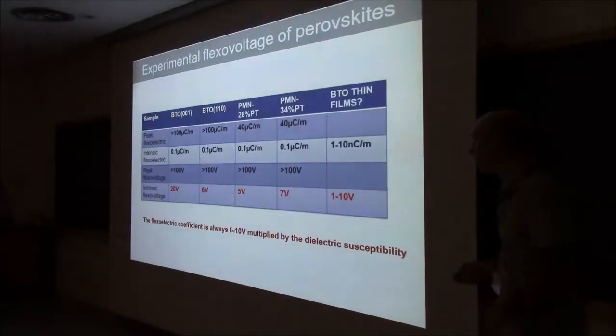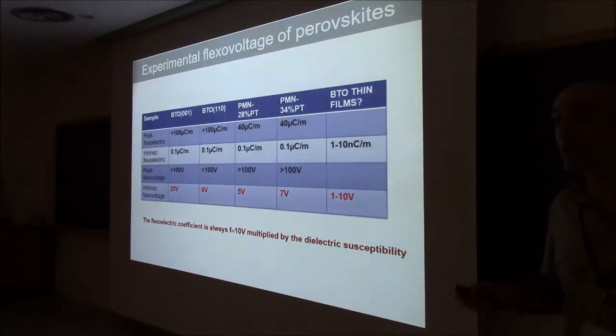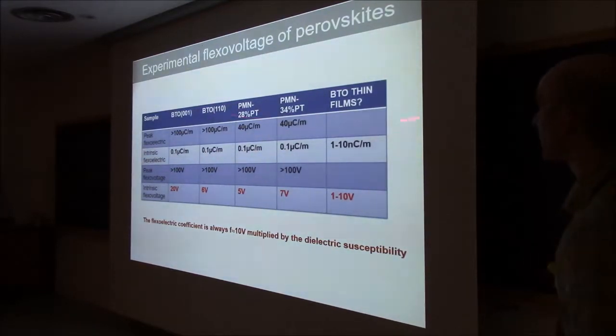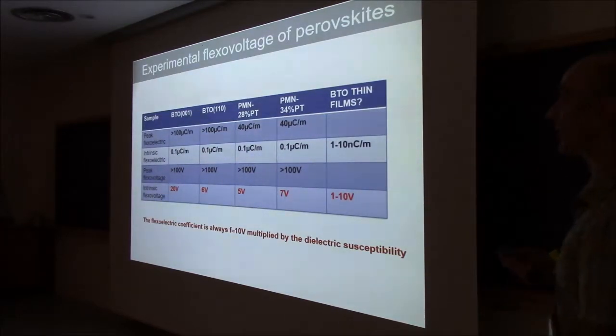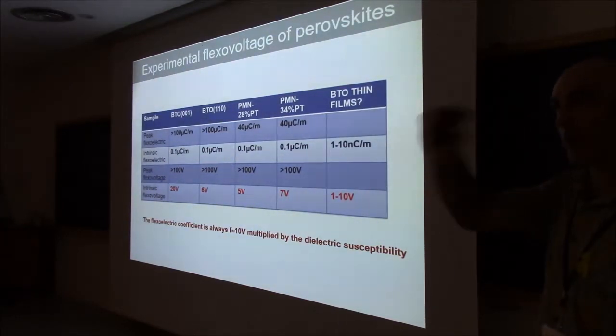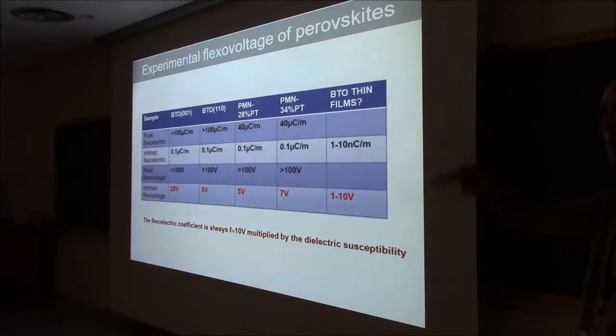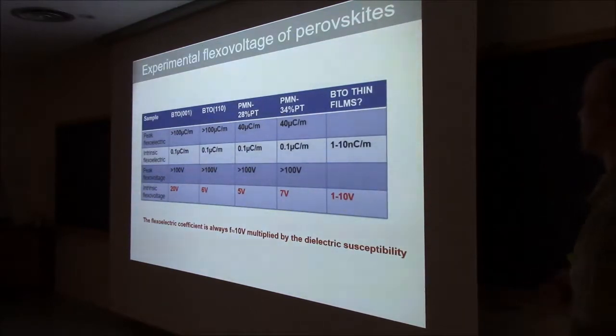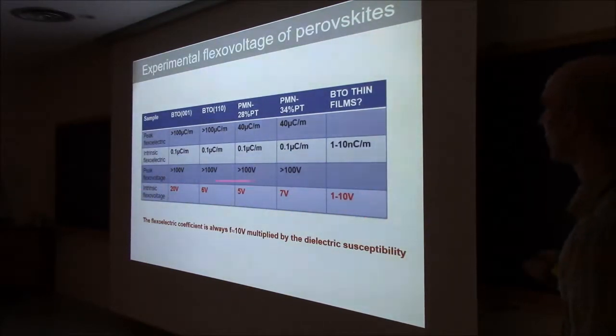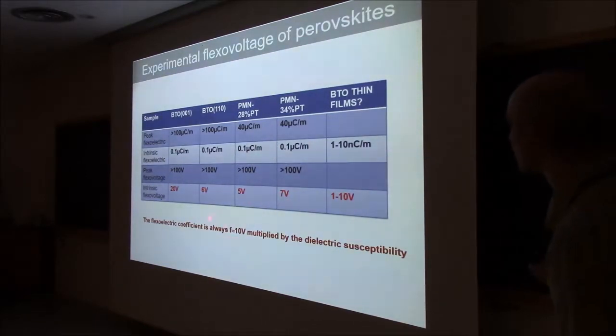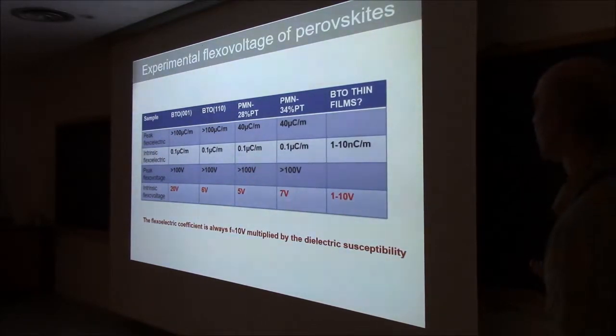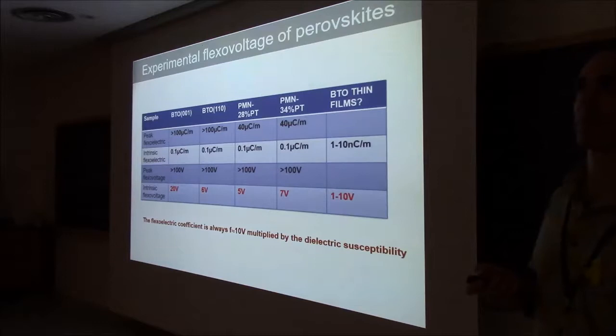And in fact, we have measured a bunch of oxides. Here I've only listed the perovskites, but I think even for titanium dioxide, this is also the case, that when you look at the intrinsic part, the one that is temperature independent, beyond any hysteresis, whatever, it's always a number of the order of about 10 volts. Okay, so the smallest we've measured is about 5 volts, and the biggest we've measured is about 20 volts.